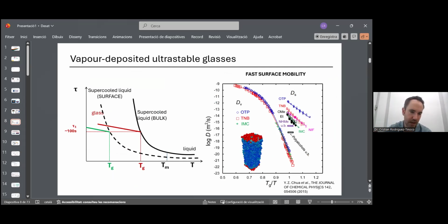The relaxation time has not been measured directly, but for example, the surface diffusion has been measured. And we see that the surface diffusion in many systems is larger, which means faster relaxation time as compared to the diffusion in the bulk. So this is the mechanism. We take advantage of this faster mobility on the surface to keep the glassy system, or the supercooled liquid, in equilibrium down to lower temperatures.